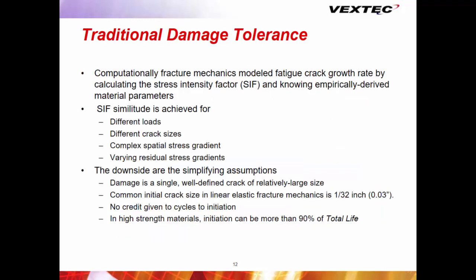And most all of these methods are damage tolerance based. Now, they're not linear elastic fracture mechanics, but they're damage tolerance based, in that you're actually modeling, on a cycle-by-cycle basis, damage that builds up. And the reason they're not linear elastic fracture mechanics is what was shown this morning. That could be the last 20% of life, and in a nickel alloy, the last 1% of life. So by the time you get to a large crack, you can be almost over with life.